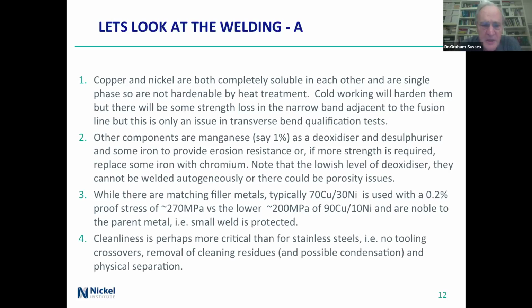And cleanliness is a lot more critical than for stainless steels. You can't allow for tooling crossovers from carbon steel or other materials, because putting iron in is a problem, but chromium can also be a problem. And you need to remove any cleaning residues, or even condensation that's got into your welding setup. One example I came across was people using air blasts to clean stuff up and getting condensation because their air blast hadn't been properly dried. Physical separation is a good way of making sure that if you're grinding something up somewhere, you don't put muck and rubbish onto your nice clean weld prep.